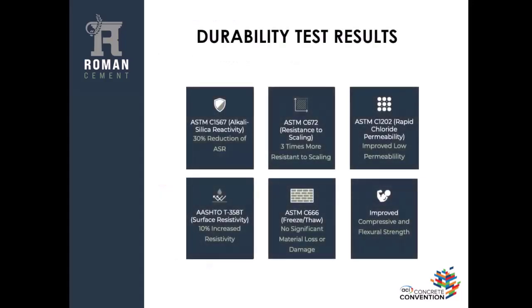Ultimately, we did some durability testing later on because that's not something we did beforehand. We took a typical concrete mix of the same strength, 4,000 PSI, used a reactive aggregate to do the ASR test, and simply by reducing the cement by 20% and adding limestone powder with no special additives, we were able to reduce the alkali silica reactivity by 30%. Resistance to scaling was dramatically improved. Theoretically, it's because our cement paste matrix was less porous, because we have a higher particle-packed cement system with the limestone powder. Rapid chloride permeability test, we improved that. The surface resistivity went up. Freeze-thaw was about the same. And then we had improved compressive and flexural strength compared to the control mix.